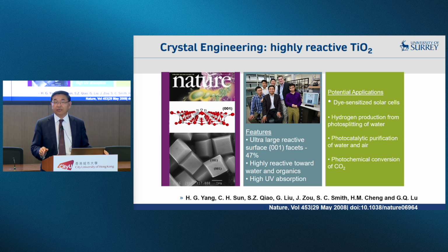So speaking of crystal engineering, we did some work on one particular photocatalyst. This was many years ago. We used quantum mechanical ab initio calculation to guide our experiment to search for the method to realize highly active facet control. In anatase crystal you have the 001 facet, shown on the slide, and the 101 facet. The 101 facet is actually the most stable, and 001 is highly active because it has unsaturated oxygen-titanium bridges. So we were the first to prove Michael Grätzel's theory, that this 001 facet can be produced stably, but no one had actually been able to do it.